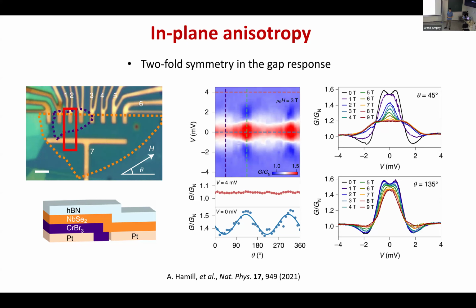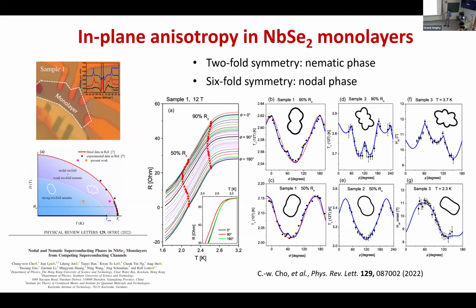Around this paper there were also several arguments. One of the arguments was that to see a C2 symmetry, one very easy way is that your placement of the sample is not strictly parallel to the field. You have to be extremely cautious with your compensation. They wrote very long text in their supplementary explaining why they're right. I don't know if they were, but when they showed this I was also very suspicious, because they just glued the sample. They didn't really have a two-axis rotator to align it, so no way to compensate. Okay, let me finish this and then I'll go to these trivial effects.